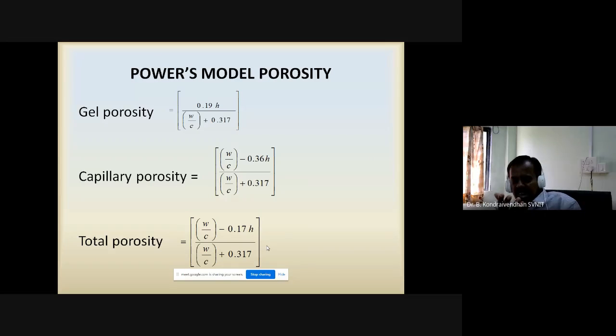Gel porosity is 0.19 H, where H means degree of hydration. I used alpha, they used H; H and alpha are the same. It is divided by W by C plus 0.317. Capillary porosity is W by C minus 0.36 alpha (or H) divided by W by C plus 0.317. These are already established and readily available, so you can directly take the Powers model porosity.